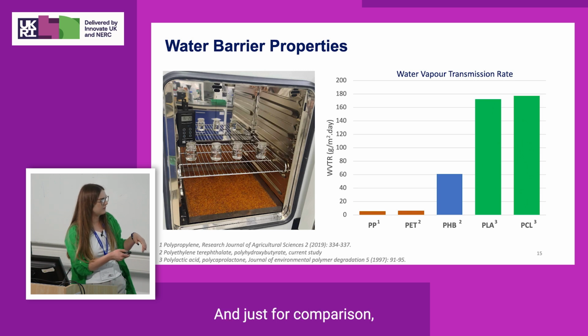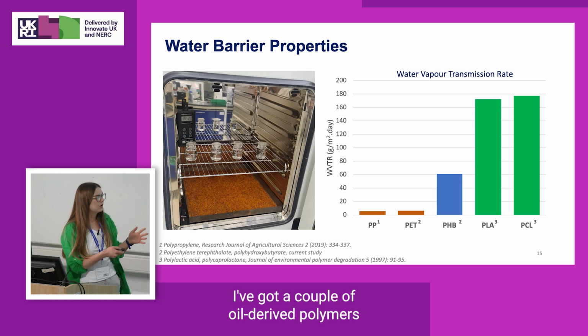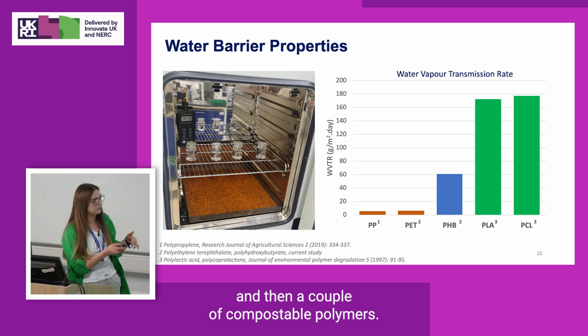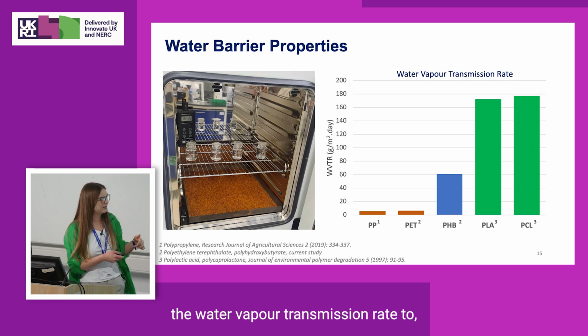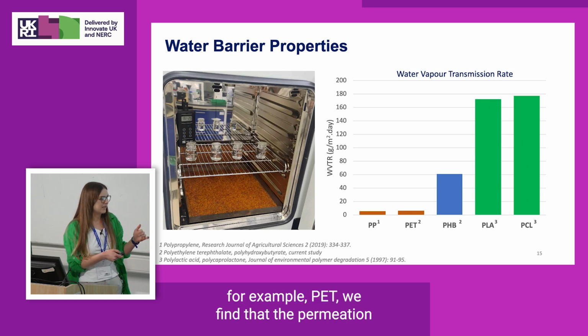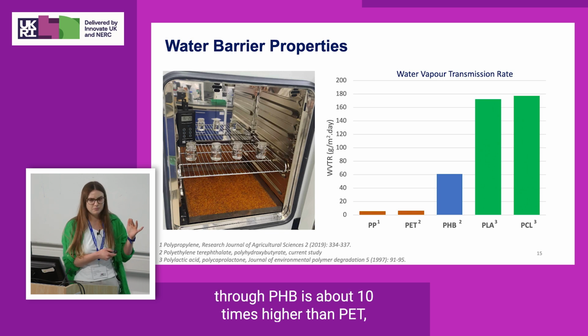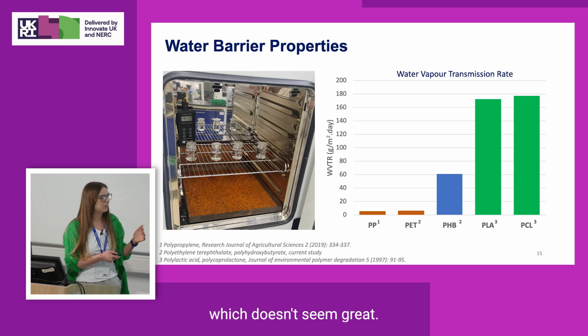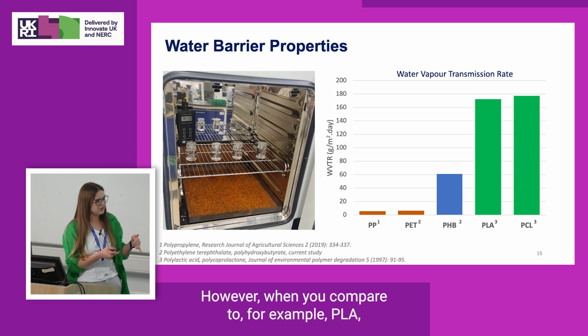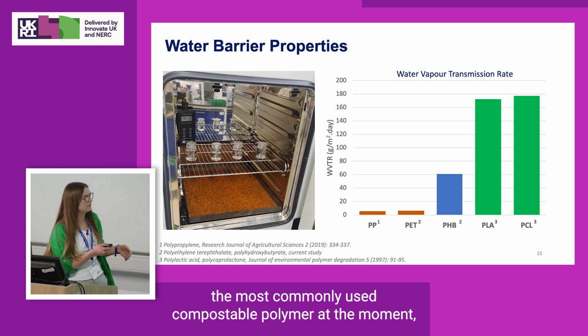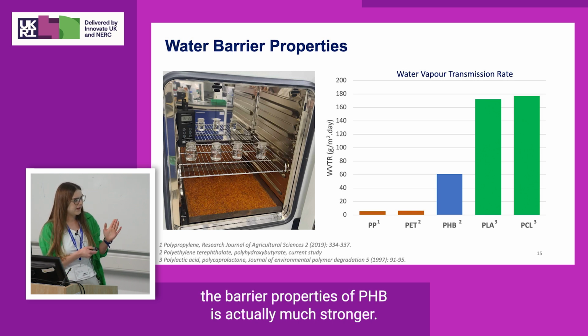So I've got PHB in the middle, and just for comparison, I've got a couple of oil-derived polymers and then a couple of compostable polymers. So when we compare PHB, the water vapor transmission rate to, for example, PET, we find that the permeation through PHB is about 10 times higher than PET, which doesn't seem great. However, when you compare to, for example, PLA, the most commonly used compostable polymer at the moment, the barrier properties of PHB is actually much stronger.